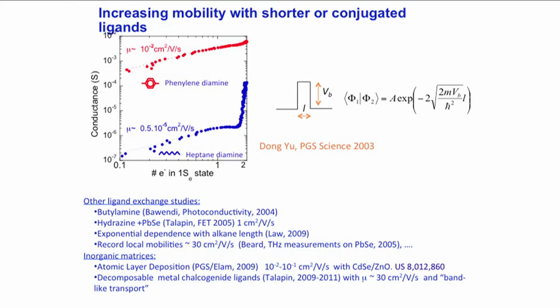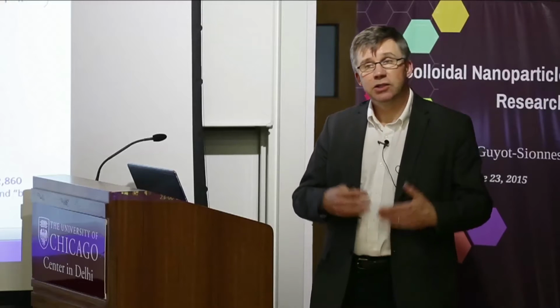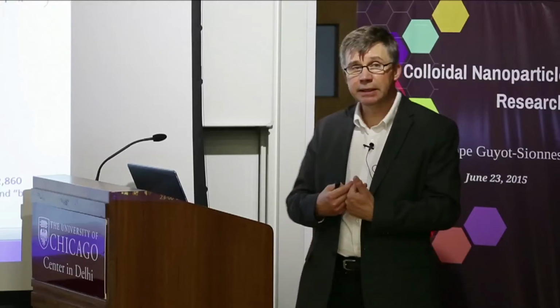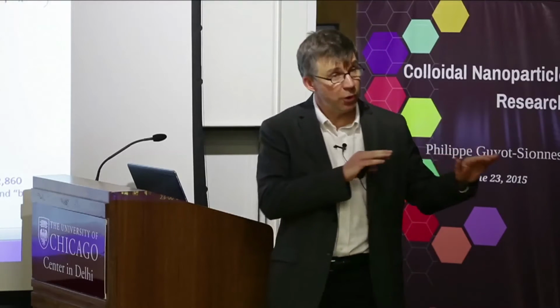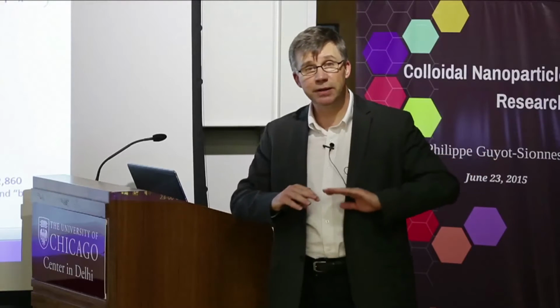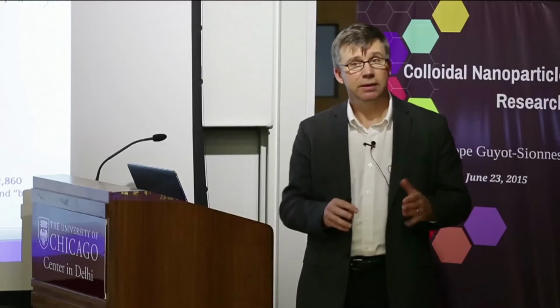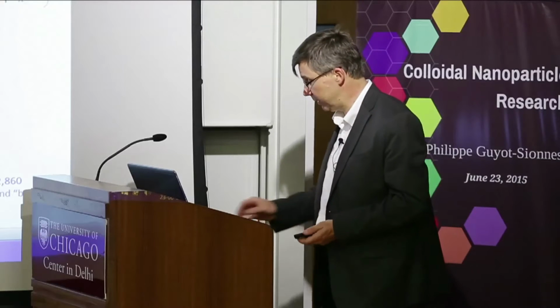And so nowadays, the mobilities, which is a measure of how easy the electrons travel through the materials, are becoming quite high, 30 centimeters squared per volt second. The challenge, I think, with such high mobility is to be sure that the electrons are actually flowing through the quantum dots rather than around the quantum dots. And I think this is still a question that has not been resolved.